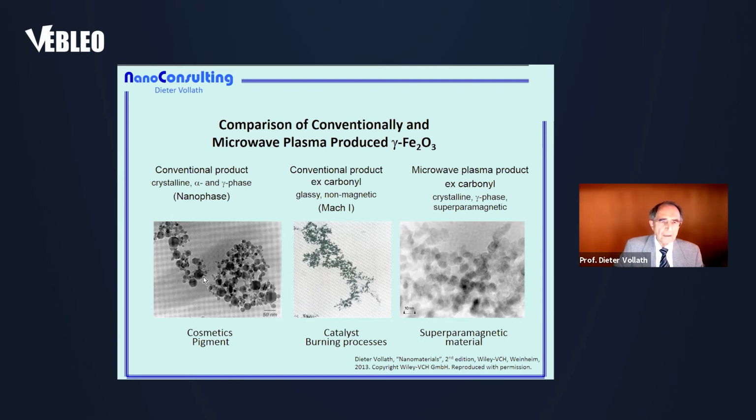The diameter ratio between the larger particles and the smaller ones is about 10 or so. Diameter ratio of 10 means a volume ratio with a factor of 1,000. This is remarkable, but there are many applications where this is no problem, for example, using it as pigment in cosmetics.